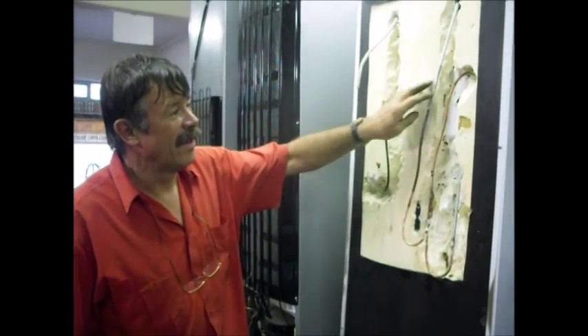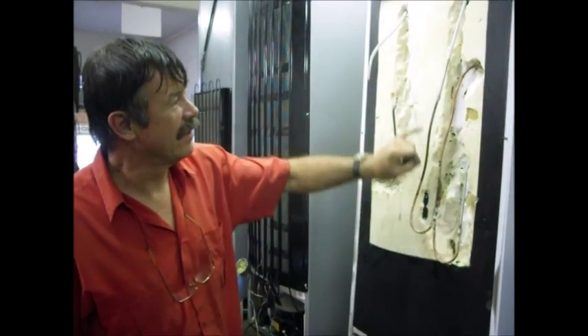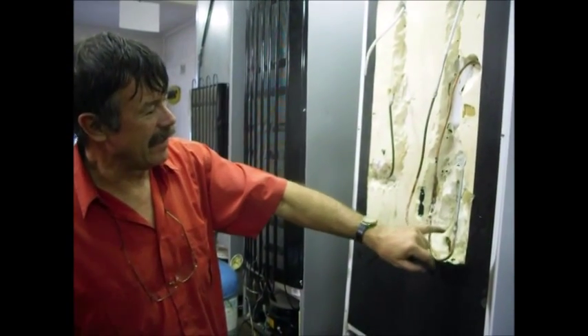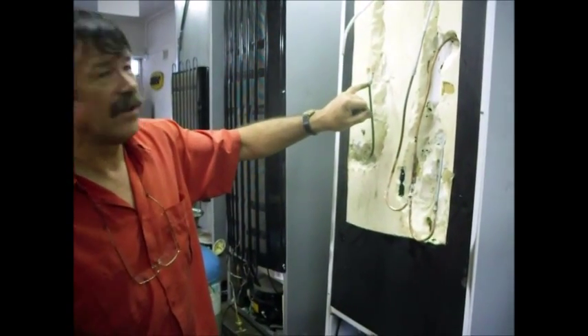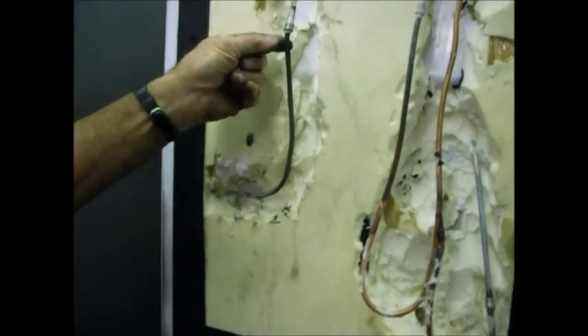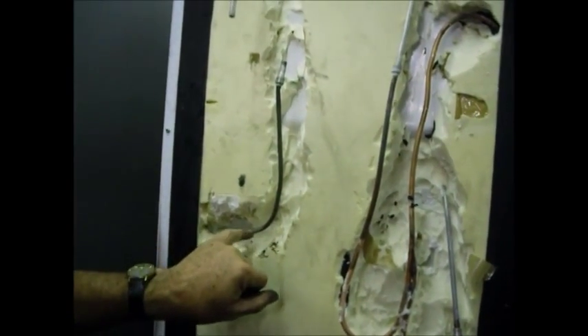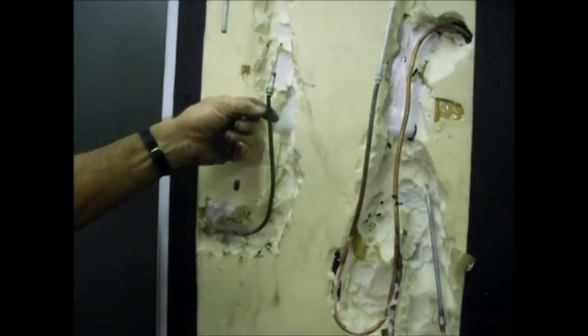This is the Fridgemaster fridge and in the back they've got aluminium, copper and steel pipes. The steel pipes are joined onto the copper and the aluminium with a lock ring. And in the factory where they put a lock ring on, they clean the anodizing which is that silver bit off the pipe and the pipe rusts through and there's a leak here.